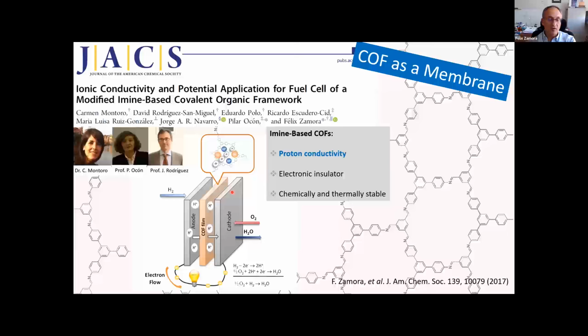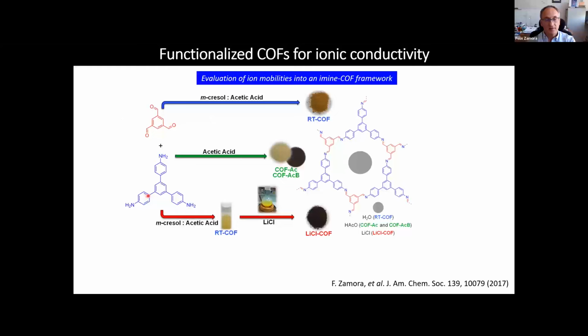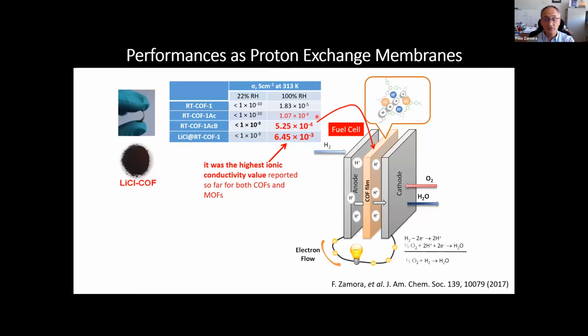So, in this work, in collaboration with Professor Jorge Rodriguez and Pilar Ocon, we produce three different COFs with the same structure. We produce a COF containing into the cavities controlled quantities of acetic acid, and one containing lithium chloride. The idea was to get materials with a nice high ionic conductivity. And here I show you the result that we got. They were relatively good. Indeed, this result was quite good.